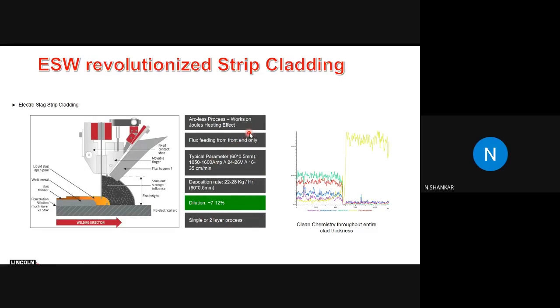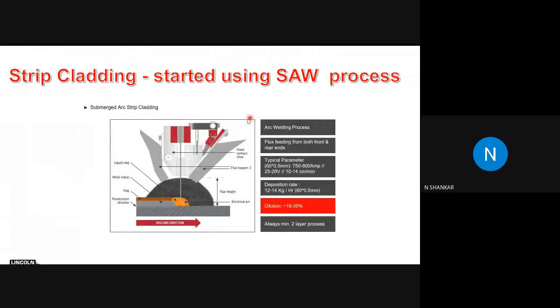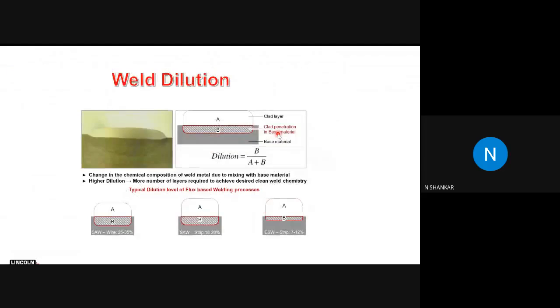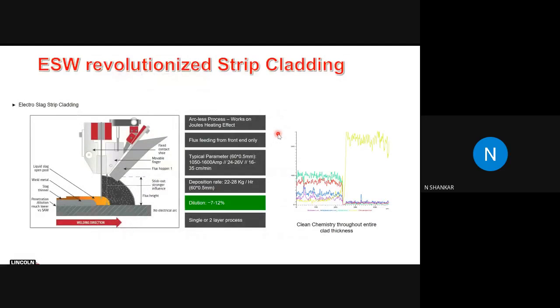It has moved from arc process to arcless process. It works on Joule's heating effect basically. So the flux feeding is also required from only one side. You would have seen in the previous slide, flux feeding is required on both sides, and arcing is done. Here it's not arcing, it's Joule heating effect that comes into picture.